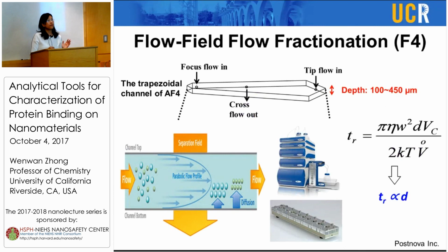So we use flow field fractionation, which is also a commercially available separation system in our group. Different from capillary electrophoresis, it uses a trapezoidal channel, and this channel is kind of like a ribbon. It's very shallow and relatively wide. But similar to CE, it also has no packing inside the separation channel, so it's also one kind of open channel separation technique. Therefore, we believe it also has very low disruption impact on the formed corona on the particle, because we incubate the particle first in the biological matrix, for example serum here, and then inject the mixture into the column, and then collect the particles at the end of the column.